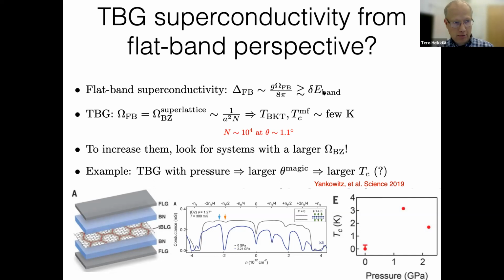But one thing that you learn in the flat band limit is that the delta is proportional to the size, the area, of the flat band in momentum space. In the case of twisted bilayer graphene, this area corresponds to the area of the Brillouin zone of the superlattice, which means that in that case the area is much smaller than the original Brillouin zone area. It's actually smaller by a factor of 10,000. But still you get the BKT temperature of the order of a few Kelvin.